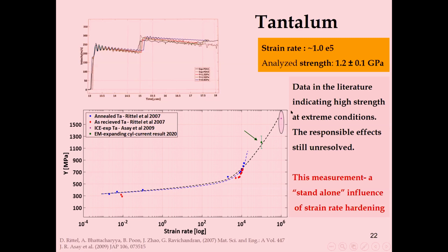And additional results which were done in the isentropic compression experiments by Zev, Vogler, and others in Sandia. And in general, you could see that the result we got is bridging somewhere between the area of 10 to the 4 to 10 to the 6. This kind of cloud which I put here is because there's not a specific measurement of strength. That's part of the problems of these kind of measurements. Some of them are measurements which are done under release and some are under compression, and they're predicting different kind of strength.